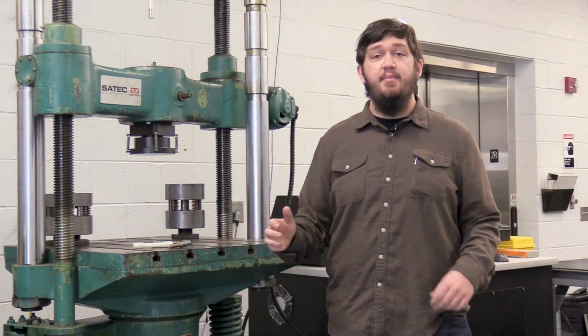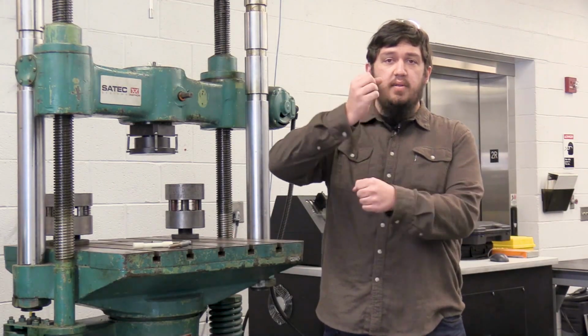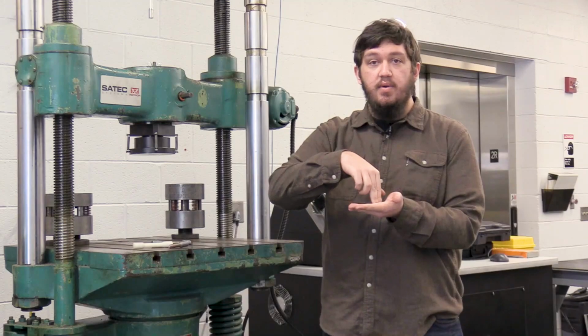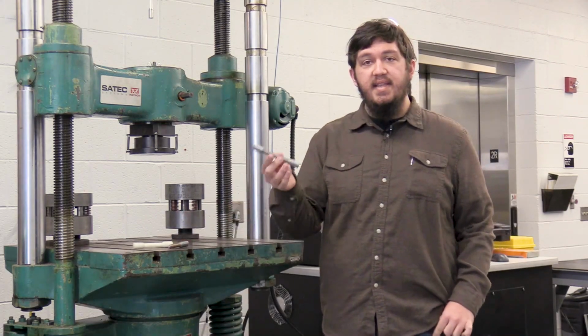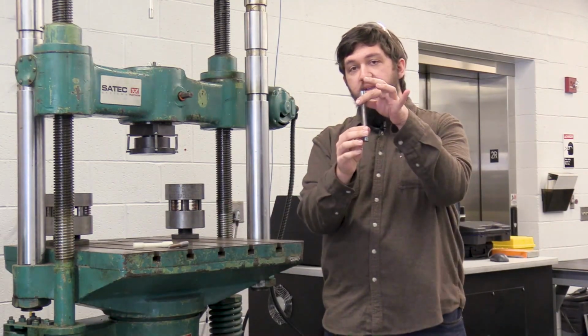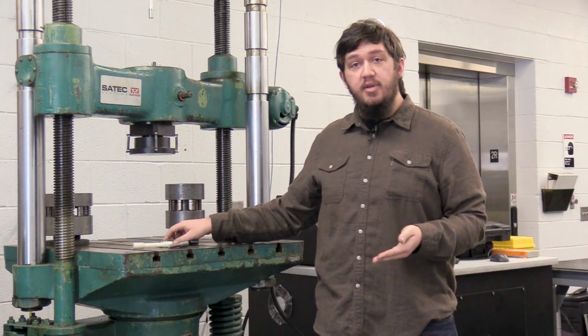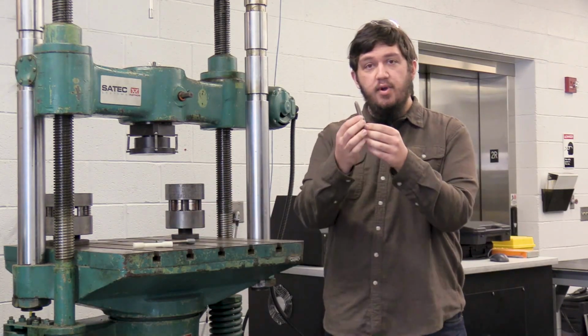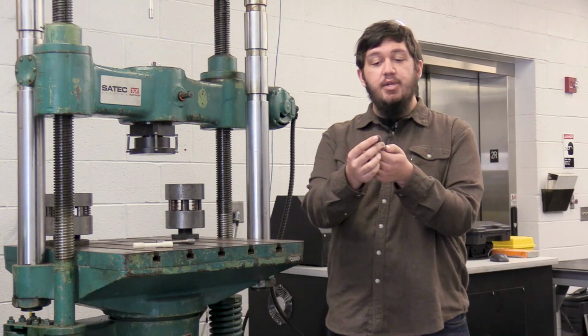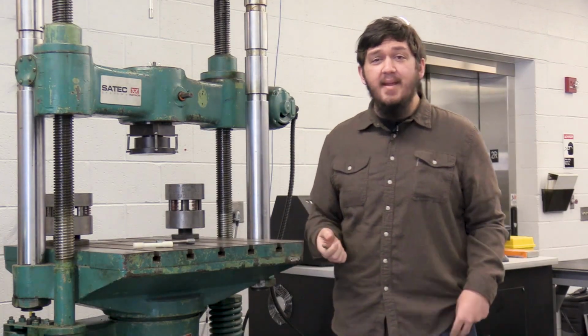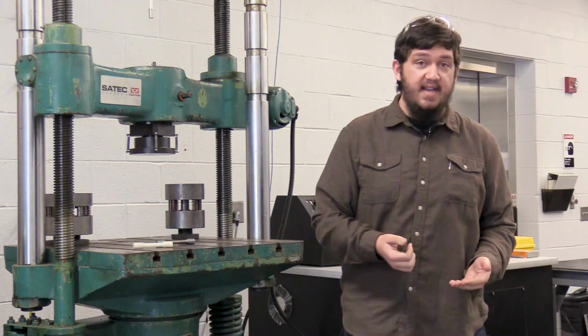What this press does is it applies a tensile, so pulling, or a compressive, pushing load. We'll use something called tensile bars. We'll pull this apart until it breaks. We measure the force at which it breaks, and then later, once it's broken, we'll actually examine that fracture surface. This tells us a lot of information about the material and how it was processed.